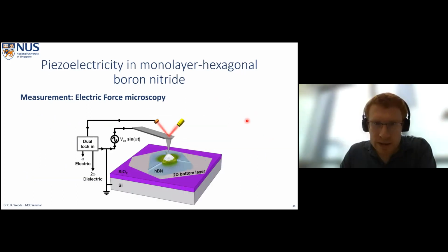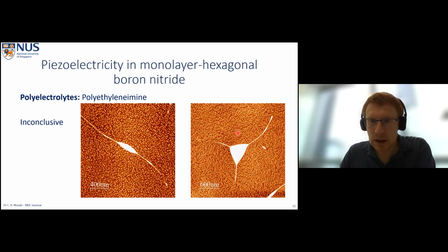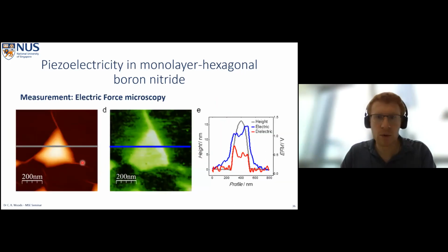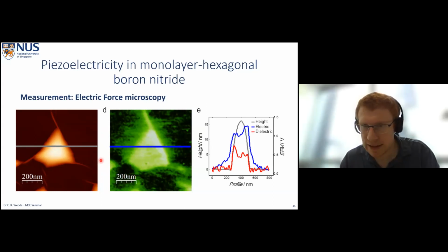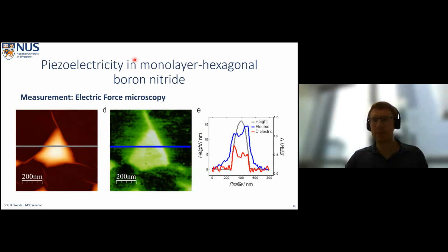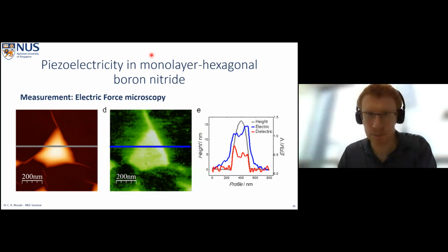So we're deliberately creating systems for this case where we have nothing here, no contamination. So we're making the sample as quickly as possible. We contact the silicon, so we don't have to do any more fabrication on the surface, and then we measure it within a day of making it, so that the polymer contamination is kept to a minimum. So actually, all of this signal we can say is really not related to topography or not related to contamination at all.